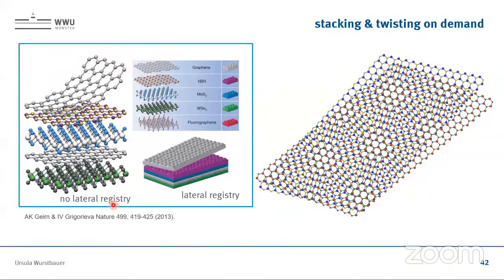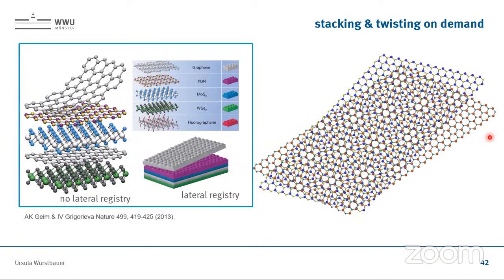And here now we use the property that we can combine these van der Waals materials on demand, because we don't have out-of-plane covalent or ionic bonding. With that, the registry, like in the LEGO here, is missing. So it's not such that we can just stack together what fits together. No, with the van der Waals interface, we can now combine any material, and there's a little bit more. So here, if we have 2 materials, we can rotate them.